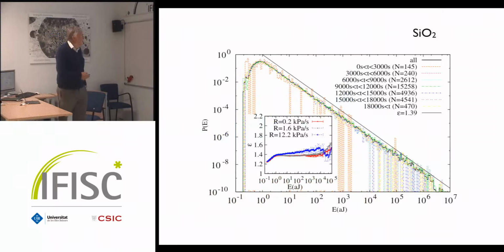you take the probability distribution function, which basically is you bin it. You take lots and lots of bins, and then you say which signal is in that bin, and so forth. I mean, that's an automatic process. And here's the energy of the avalanche. And you can see, first of all, we are talking about 6 orders of magnitude. Now, 6 orders of magnitude is not a triviality. 6 orders of magnitude is a lot. If you go 10 to the minus 6 meters, that's pretty small, right? Or you go up from 1 angstrom, 6 orders of magnitude big, it's quite big. So, you know, you have a huge range here.